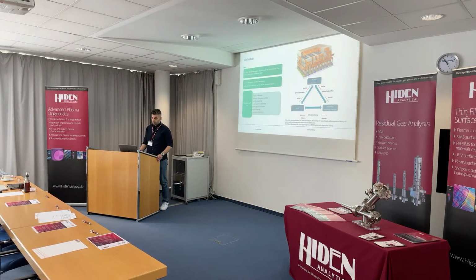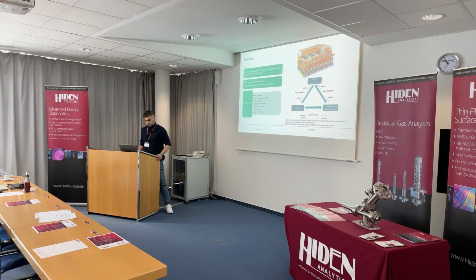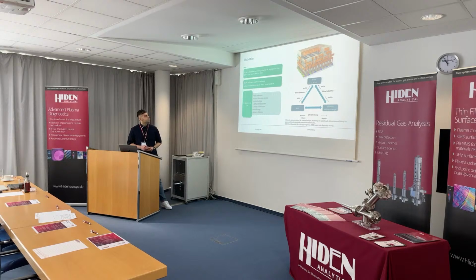Let's start with motivation. To aid the development of process for back-end of line and interlayer dielectric, and due to the increase in material limitation and technical difficulties due to device miniaturization, we face problems such as etch uniformity, critical dimension control, etch selectivity, etch profile expansion, charge accumulation, etch damage, and pattern distortion. Here you can see a photo and illustration showing the interlayer dielectric. Here is the copper line, and this is the dielectric, and here is the back end of line.